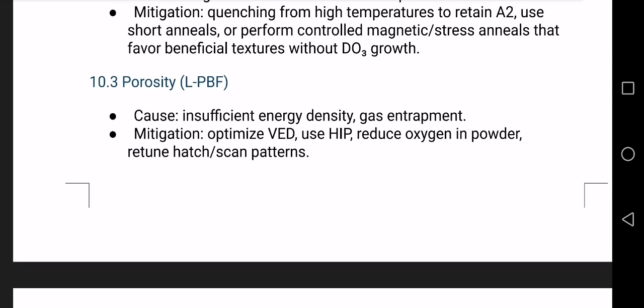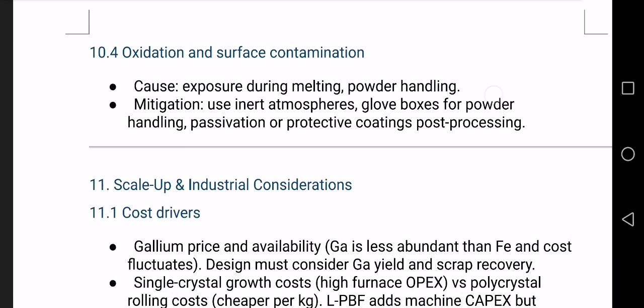Porosity in LPBF parts. It is caused by low energy density and gas entrapment, and its solution is to optimize printing parameters, use HIP, and improve powder quality. Oxidation and surface contamination. Its cause is exposure to air and poor powder handling. Solution is inert atmosphere, use glove boxes, protective coatings.